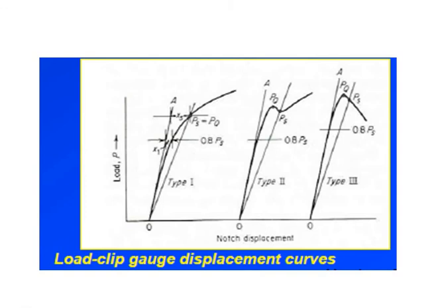So this is the first part of the diagram, the type 1 diagram, for a too ductile material. In the type 2 and type 3 diagrams, the procedure is exactly the same. The load displacement curve is drawn for all of them, and the tangent is drawn in the same way. From there, 5% less, you have drawn a PS point, then from there 20% down is 0.8 PS. The same thing in all three. Type 2 and type 3 are drawn the same way as type 1.